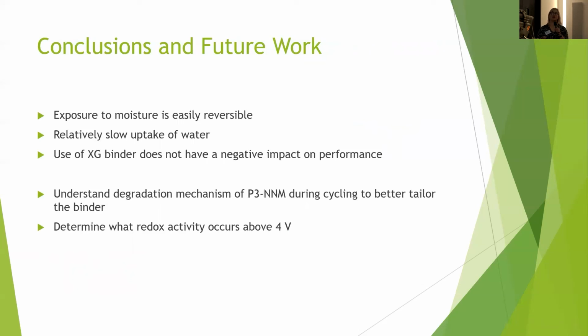So in conclusion, the structure I'm researching is P3 sodium nickel manganese oxide. It's fairly stable in moisture and is easily reversible back to the pristine material. And there's no negative impact on the electrochemical performance. So we're able to use a more sustainable binder here. In the future, I need to figure out why the capacity is fading so quickly in certain voltage ranges, whether it is this oxygen redox or there are more severe structural changes going on.